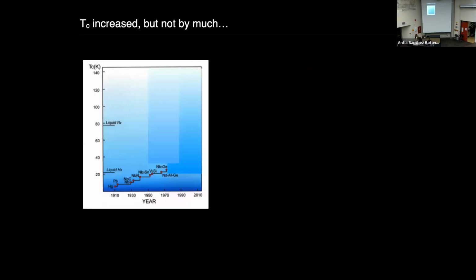So the years went by, and more superconductors were being discovered. What you see in this graph is just a plot of Tc versus year, and in red, even though here it looks darker, you see different superconducting materials. But you can also see that the Tc didn't really go up by much, somewhere around 20 Kelvin in the span of 60 years, right? So not very good, especially if you're looking for a room temperature superconductor.